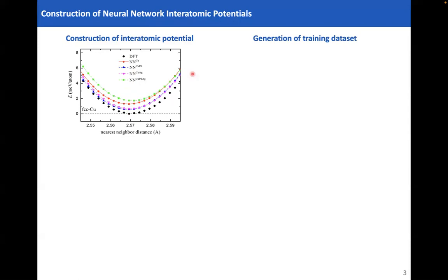This is an issue because ideally we want to always reuse the data and avoid regenerating all these databases. And the scale of the error that we are seeing is typically of the order of the machine learning error itself. So in particular, in the application to materials prediction, which is very sensitive to these errors, this is not really good.